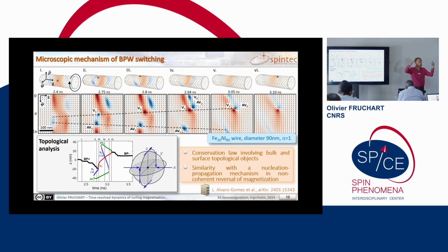Okay, here you have a system, the periphery is hundreds of nanometers. So instead of everything going radial, which would cost a lot of energy, you nucleate somewhere and you propagate along the perimeter. But you also have to consider the bulk. And I do not enter into details, but you can follow the different objects, the vortex, anti-vortex on the surface, the Bloch point inside, and link topology inside and outside for conservation.